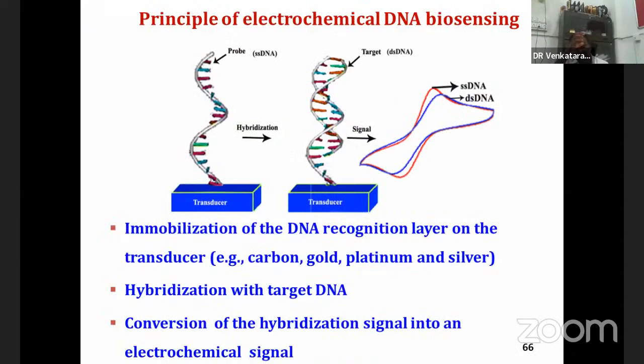non-enzymatic DNA molecular sensing, where we directly put a single stranded DNA and add the double stranded target DNA, and we form the double stranded DNA, and before and after you can monitor the signal magnitude changes between the single strand and the helical formed double stranded DNA. For this purpose, you need 4 steps: immobilization of the transducer, hybridization of the target, and the conversion of this hybridization signal into electrochemical signal.